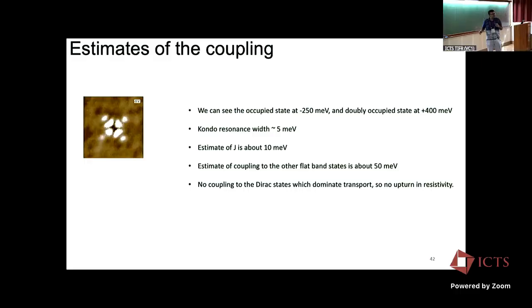And one of the very interesting aspects of the Kondo in this particular material is because of the way these states are constructed, these bound states in the continuum only talk to the other bound states in the continuum. They don't talk to the Dirac bands. They're orthogonal to the Dirac bands. And so if you measure transport, in a transport measurement, you actually won't see the Kondo upturn because they're completely unaffected by this scattering. But if you do a spectroscopy experiment like what we do, you can actually see this. Okay, so that is Kondo.